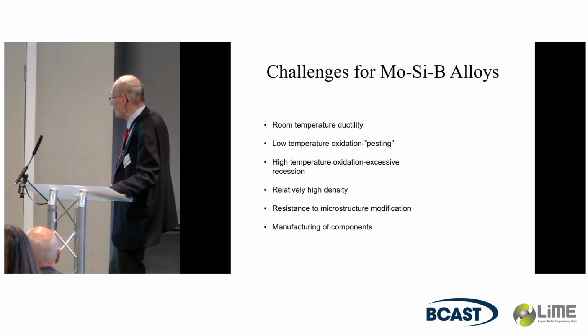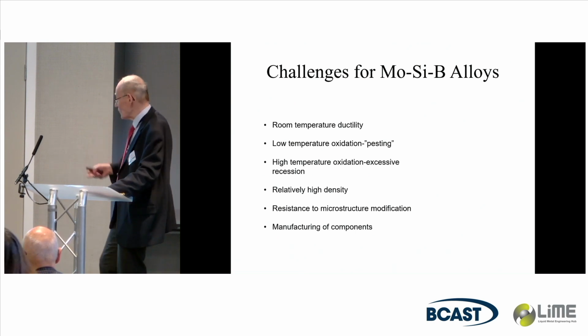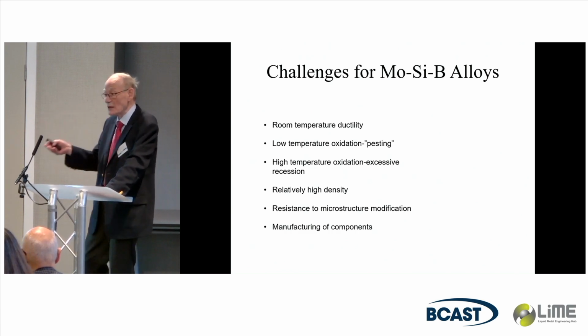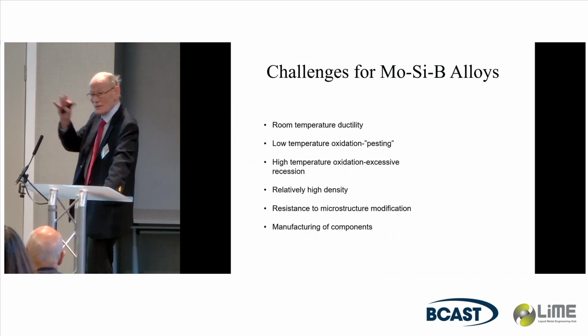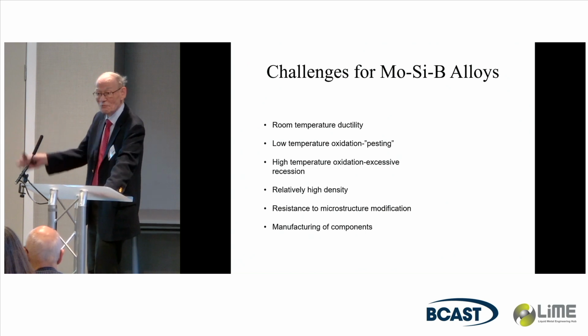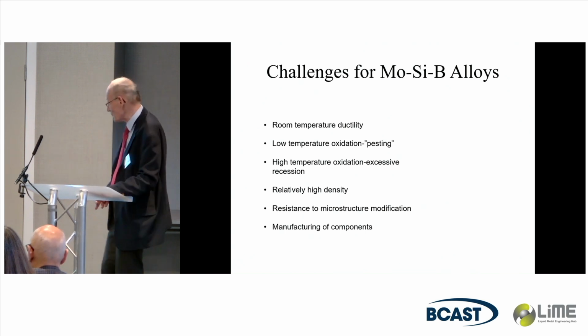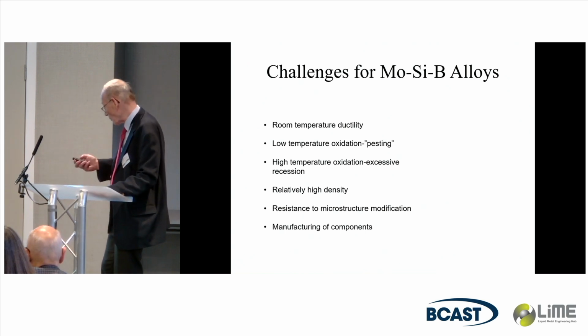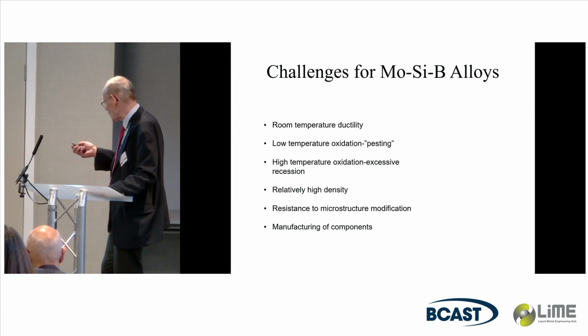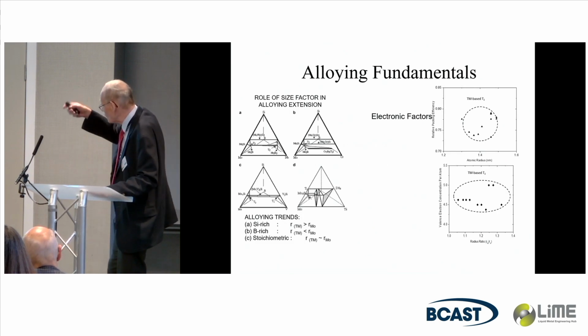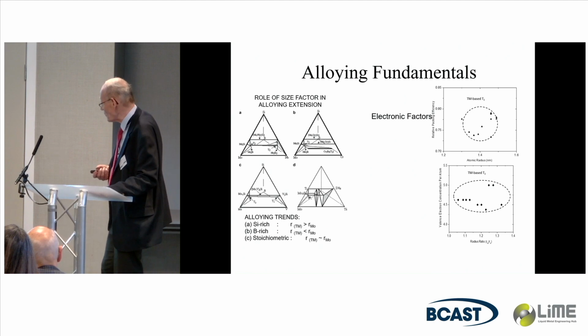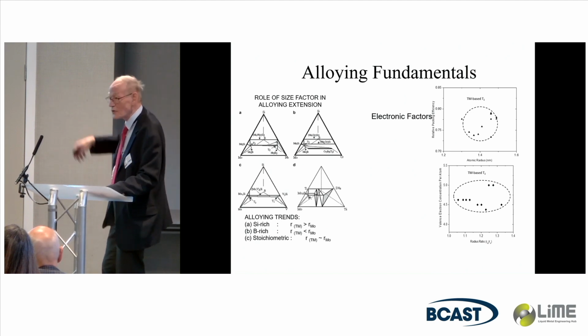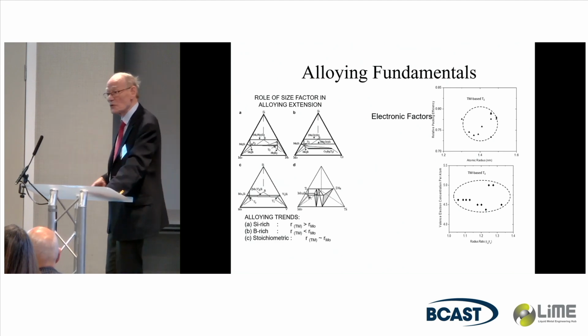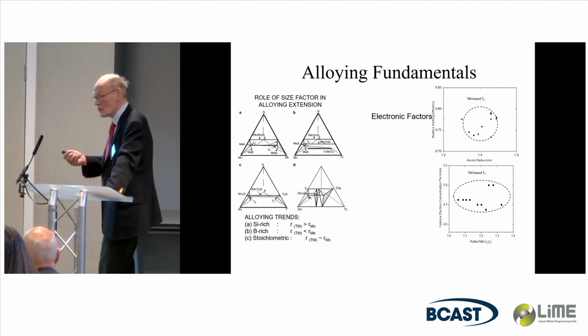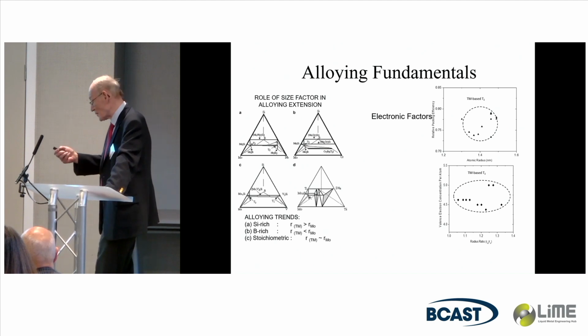Resistance to microstructural modification. The problem with these very high temperature alloys is, once you make them, you can't change them. You want phase stability at high temperature. That means you can't do diffusional processing in manufacturing components. So we've solved each of those problems. The first is using what I call the Hume-Rothery rules of intermetallics or silicides. We have a size difference and electronic factors that allow us to predict solubilities with good accuracy.